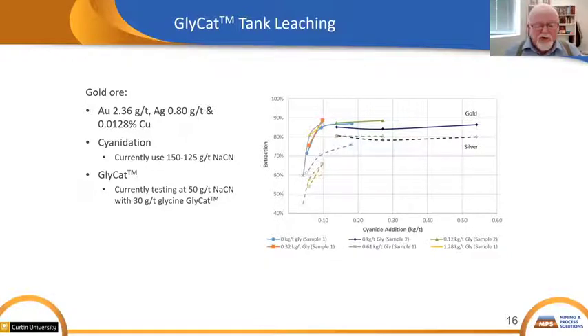So in the first domain, the light blue line is no glycine, which you can see there, and you can see the silver equivalent down below it. The orange line is 0.32 kilos per ton glycine, which you can see that's the best in the domain and the best of both series at 0.10 kilograms per ton sodium cyanide and 0.32 kilograms per ton glycine. The gray is experiments represented at 0.6 of a kilo per ton, and the yellow at 1.25.